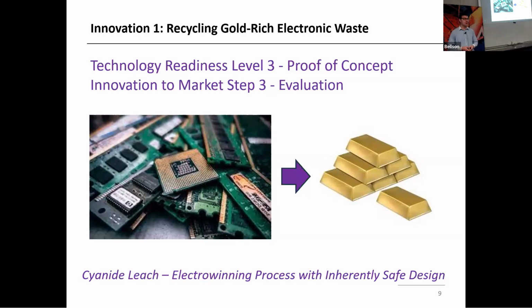We did some leaching scoping studies from different leaching approaches, and then we ended up favoring cyanide. But of course, cyanide being deployed in a small-scale recycling application is immediately a bit of a safety concern. So we designed an integrated leach electrowinning process with what we call inherently safe design. So no matter, even if the process is upset or something goes wrong, it's almost impossible to make HCN gas, which is the main concern about use of cyanide.